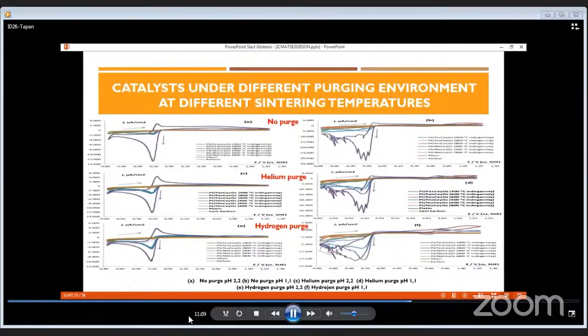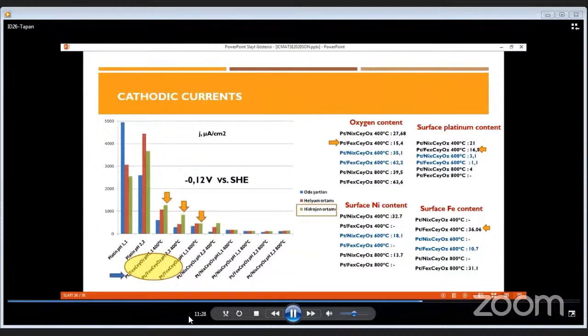When we studied the effect of hydrogen purging at different pH and different sintering temperatures during cyclic voltammetry, it showed that 400 degree reduced samples are activated under hydrogen purging from pH 1.1 and 2.2, giving high reduction currents. Ordering catalytic currents at different conditions, we see that the dominant parameters are firstly hydrogen purging, secondly the catalyst type, and thirdly the reduction temperature.